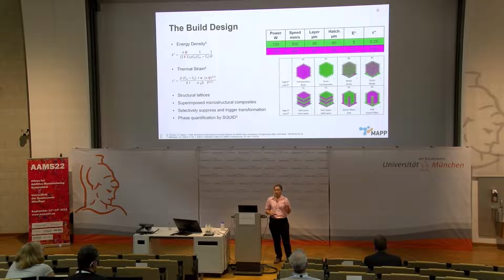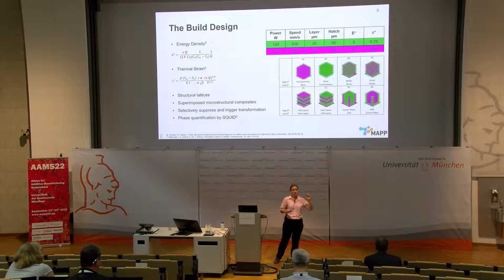So we started off with classifying it as a uniform structure, so the A1 and the A2 have just got those parameter sets applied uniformly. We've then looked at what if we split the geometry between the nodes and the struts, looked at horizontal layers and looked at vertical pillars. Picking up from a couple of the talks yesterday on lattices, there's also the opportunity to treat these as precipitates. So if we have one of those materials as a precipitate phase within a matrix of the other one. But what we're looking at is selectively suppressing and triggering that transformation by using strain, and that's the inbuilt strain.